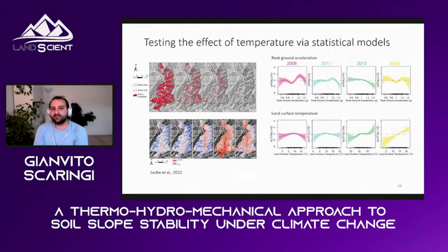But, and this is my last slide, another successful case that we have already published in Scientific Reports is the following one. We took the inventory of landslides in the epicentral area of the Wenchuan earthquake in China. And this area is, of course, dominated by a single trigger, the earthquake, and a single lithology, which is poor in clay minerals, actually. And we analyzed the patterns of remobilization of co-seismic landslide deposits for 10 years after this strong earthquake. We compared it with the temperature of the slopes, the surface temperature of the slope that could tell you something also of the underground temperature, of the basal temperature of these landslides.